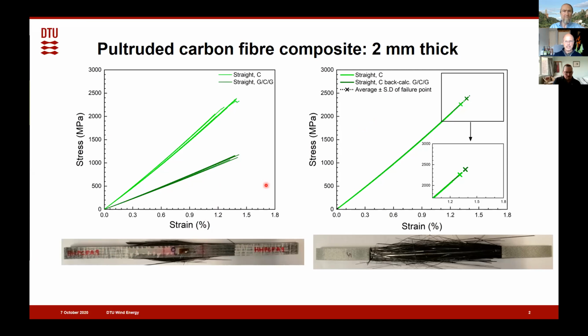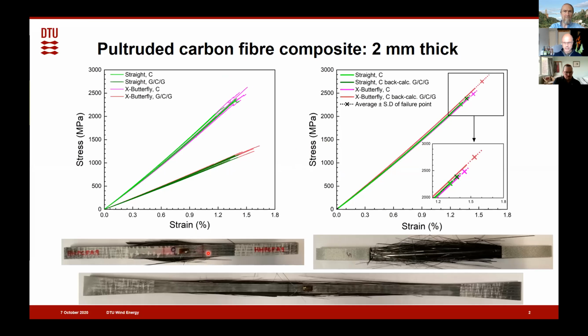But then if we subtract the glass fiber effect, then we get the stress value in the carbon fiber. The strain to failure, we just take the values here and put over here. So we can see that the strain to failure is larger for the case where we have this constraining layer on both sides of our pultruded profile.